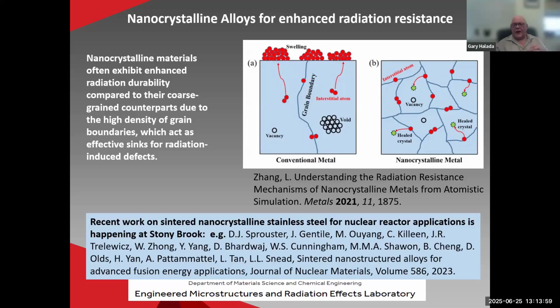And then all the crystals are packed together, and that's what a solid material looks like. However, a nanocrystalline material has been treated so the crystals are very small. Now, why that's important is that a lot of the defects that are formed due to radiation can actually move to grain boundaries, which are the spaces between crystals. If it's nanocrystalline, you have a whole lot of these grain boundaries, and these little defects can get eliminated or stuck there. And in fact, we're doing a lot of work on that at Stony Brook.